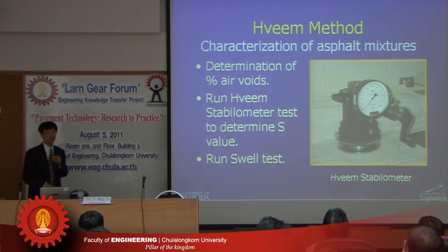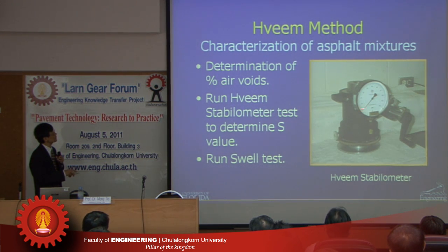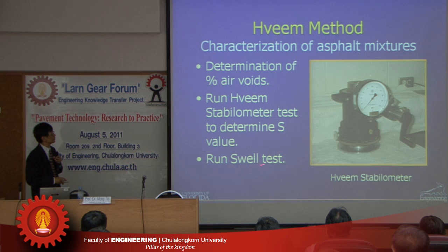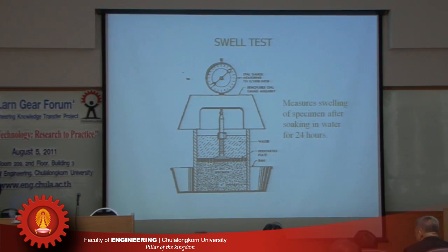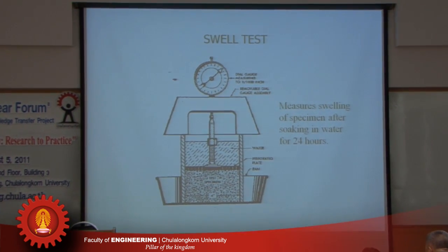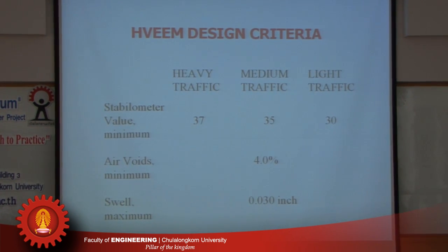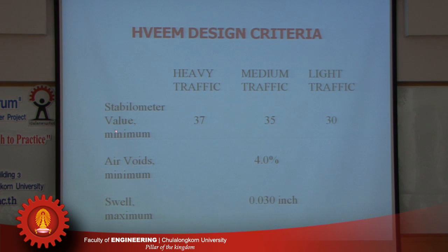In the Hveem method, we measure the Hveem Stabilometer value using the Hveem Stabilometer, and it also measures the air void of the compacted mixture. Another test is the swell test. Basically, the specimen is soaked in water for 24 hours and the swelling of the specimen is measured after soaking. The criteria require a high enough Stabilometer value. The air void needs to be at least 4%, and the mixture must meet the swell test — it should not swell too much.